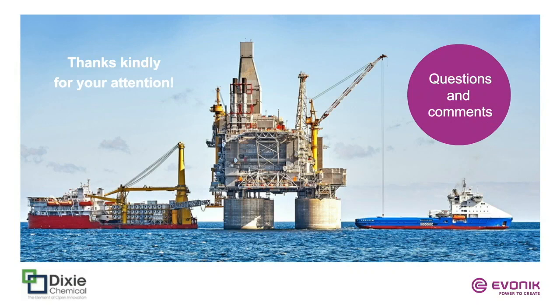Well, yeah, I think that you're using the microspheres, the additive, to give you the density, give you the compressibility you want. If your formulation, your agitation is bringing a lot of air into the system, you need to really thoroughly degas ahead of curing, so that you really are in full control of the material that you're working with. If you introduce various amounts of air or other gases in the system ahead of cure, then you're not going to be seeing the benefits you think you are based on the formulation and the type of microsphere that's used. The nice thing is that these type of formulations are pretty clean. They're solvent-free, so you're not introducing any concerns regarding porosity that way in terms of solvent liberation. And the samples that we have seen and that our testing partner continues to prepare, rather straightforward methods, nothing too sophisticated to mass cast these, right.